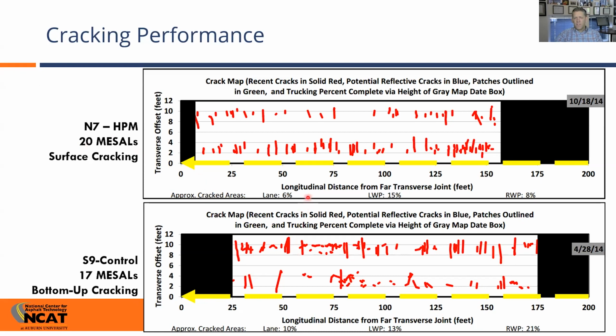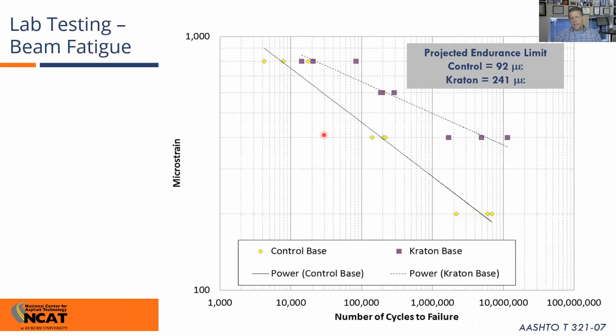And then number 2 is, and I don't have a picture of it, the maps that you see look similar, but when we did forensic coring and trenching of these sections, all the cracking in the high polymer section was confined to the surface. Whereas when we did the same kind of forensic examination in the control, we had cracks that went all the way through. So this had bottom-up cracking, and the high polymer did not have bottom-up cracking, which again wasn't a surprise.